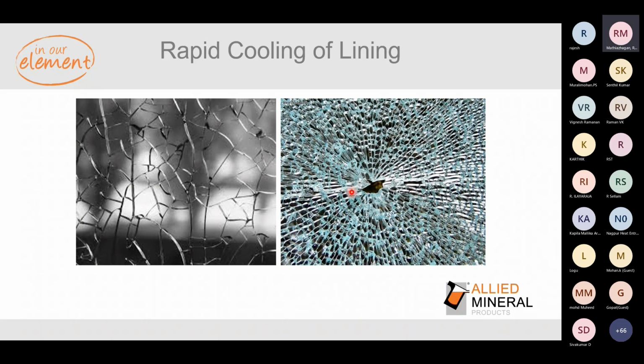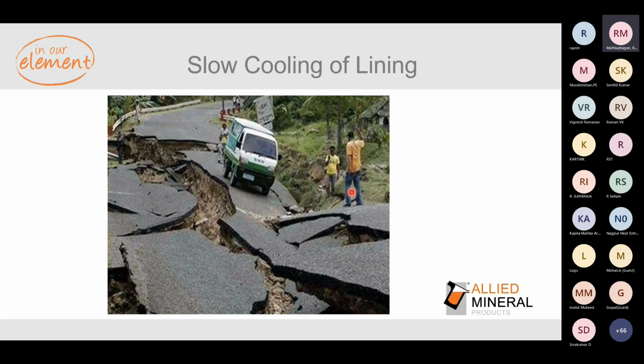This has still not been widely followed, but we keep recommending it to our customers, and we try to educate them on how important rapid cooling is for the lining. This will help to minimize the large cracks and create a lot of smaller cracks, as I showed in the picture. These will easily seal up if you follow a proper cold start procedure recommended by the refractory supplier with the help of thermocouples. Slow cooling will always have fewer cracks, but wider cracks, and these will be hard to seal up.